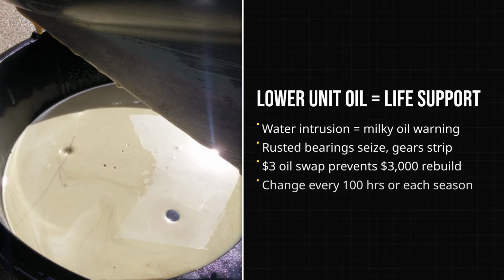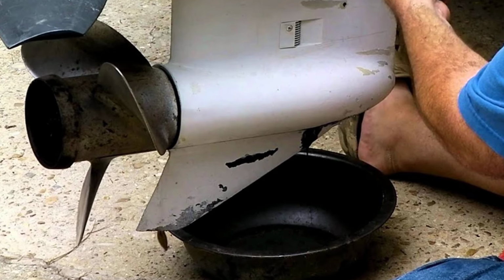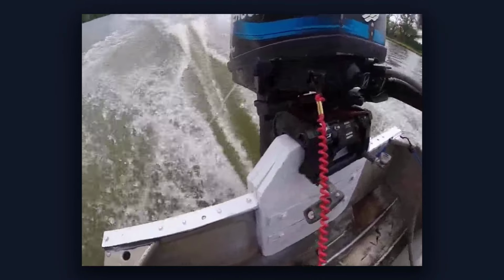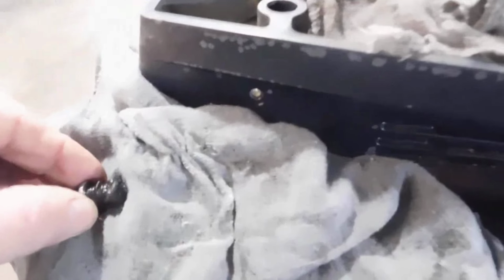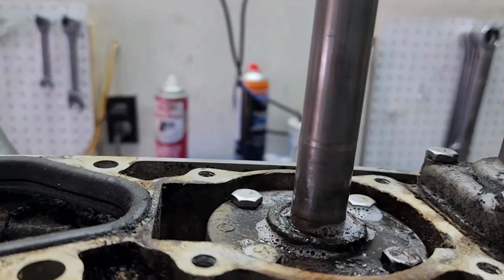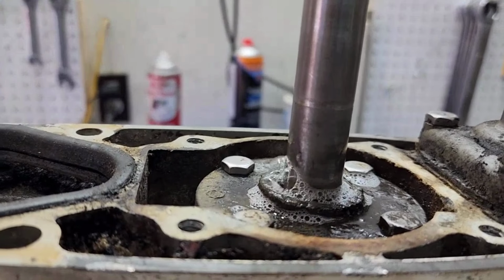Factory service intervals often recommend lower unit oil changes every 100 hours or annually, but experienced boat owners change it twice per season, especially if they run in saltwater or hit submerged objects. When you drain your lower unit and see metallic flakes, gray sludge, or that telltale milky appearance, your seals have failed and water is getting in.